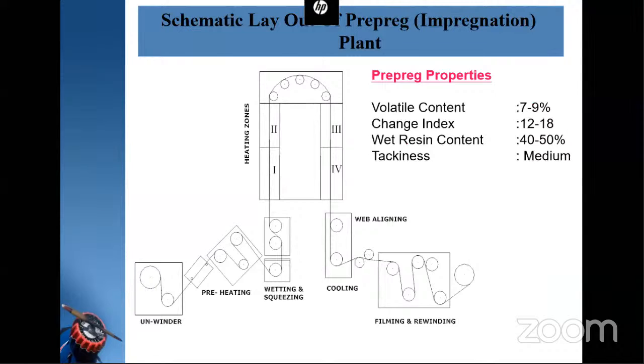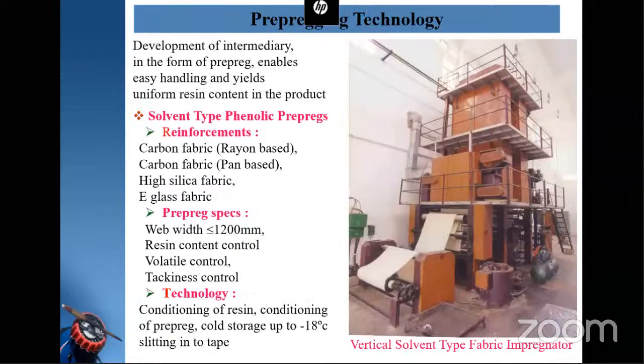So in this way we can make prepregs and keep them under cold storage for a maximum of 1 year. Here we have to maintain properties like volatile content, Change Index, wet resin content, and tackiness of the prepreg. Here you can see this actual prepreg plant which is available in our advanced systems laboratory, where we regularly impregnate the fabric with the resin system using phenolic resin. This is a vertical impregnation plant, as we call it.